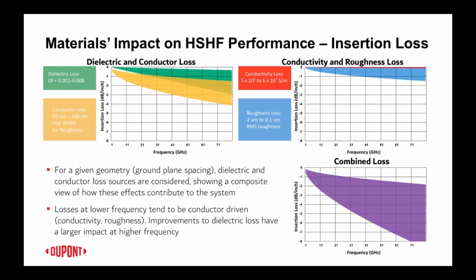The next portion is up in the top right of the slide here, where conductivity and roughness of the copper have their effects. Now, conductivity of copper is a fairly narrow range, and what's shown here in red is actually a broader range than what we're going to find in electrodeposited and rolled copper foil species that we're likely to use in our laminate systems. The loss, on the other hand, is pretty representative of what you can find out there, from some of the rougher electrodeposited coppers to some of the smoother varieties of electrodeposited and rolled copper foils. And combined losses for the whole system, dielectric, line width, conductivity, and roughness are shown in the graph on the bottom right.